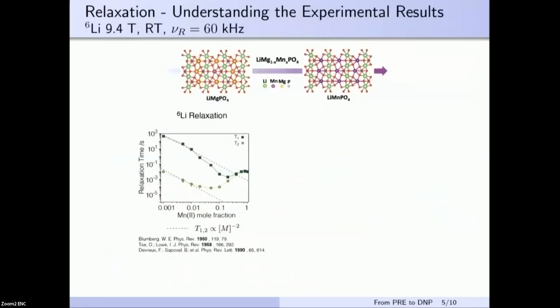So here I'm showing you the lithium-6 relaxation times as a function of the concentration. In the low concentration regime, they follow nicely the expected behavior shown here in dashed lines, which is that the relaxation time decreases with the inverse square of the concentration of paramagnetic species. But then at some point, we start deviating from this expected behavior. You can see that T2 drops slower than we would expect. And then at some point, it actually even starts increasing, so the T2 is getting longer with increasing paramagnetic concentration, which is very counterintuitive at the beginning.